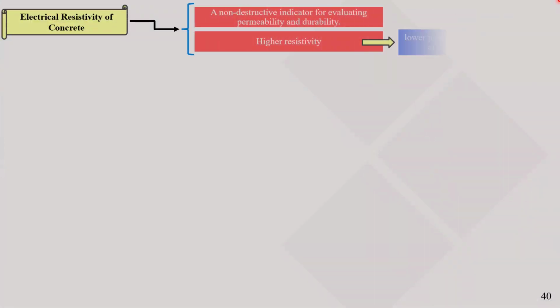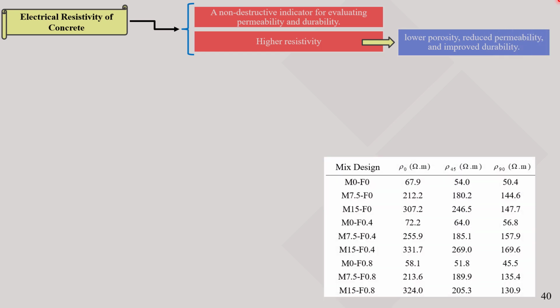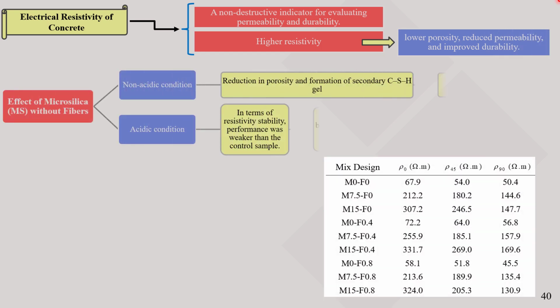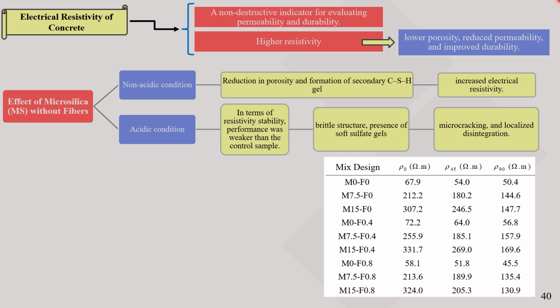We now turn to the volumetric electrical resistivity test. This test was conducted to evaluate the durability and permeability of concrete. When examining the effect of microsilica without fibers, under non-acidic conditions, increased concrete densification led to higher electrical resistivity. However, under acidic conditions, increasing the microsilica content caused a relative decrease in resistivity compared to the reference sample.